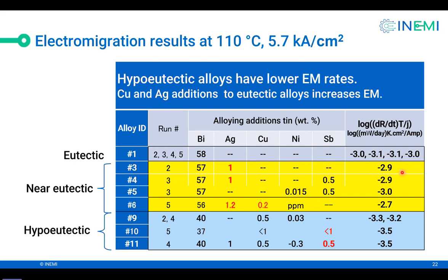Now, this yellow box is near eutectic, but it has alloying elements like silver, copper, nickel, antimony. Notice that because of silver addition, this value is now -2.9. So this is higher electromigration. So silver addition increases electromigration. And if you add 1.2% silver and 0.2% copper, it goes even higher. Note that smaller minus values mean a higher rate of electromigration. So silver addition to near eutectic solder increases the rate of electromigration.